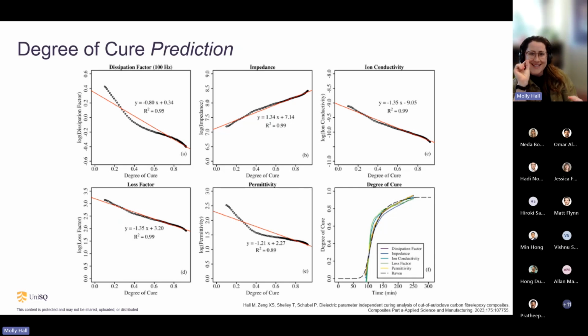And I say the prediction is in italics, and I say it's a hopeful term because if you can determine that these equations are sort of law for these materials, which we have some indications that they could be, you could theoretically use these equations to predict any degree of cure as the component is curing. So I think this one has some very interesting promise.